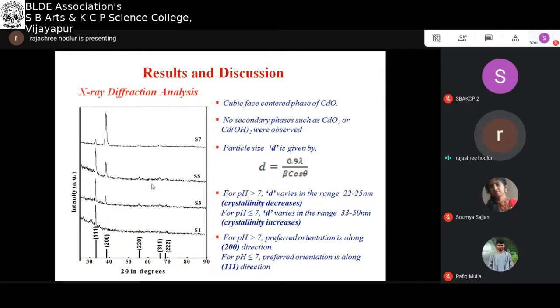And using this liquid phase approach, that is the spray pyrolysis technique, we were able to not only tune the particle size, we were able to tune the electrical conductivity as well. So what we observed is, this X-ray diffraction spectra mainly shows that it exhibits the cubic phase of cadmium oxide, and the importance of spray pyrolysis is that especially for these metal oxides, it may be zinc oxide, it may be tin oxide or cadmium oxide, we observed no secondary phases or impurities.